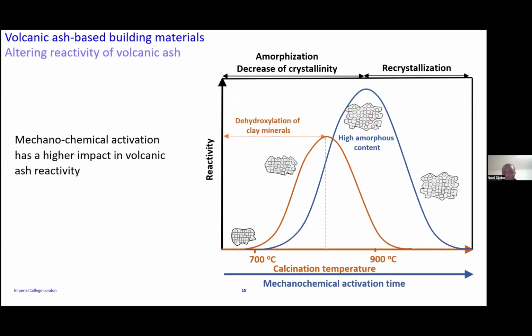The two methods that can be applied are the calcination of the volcanic ash and the mechanochemical activation. What I mean by the calcination is you can just take your volcanic ash and put in a furnace and heat up to 700 or 800 degrees to calcine it. But that is what is happening with clay. Because when we take clay in natural state, it is not reactive. But to make it reactive, you need to calcine it.